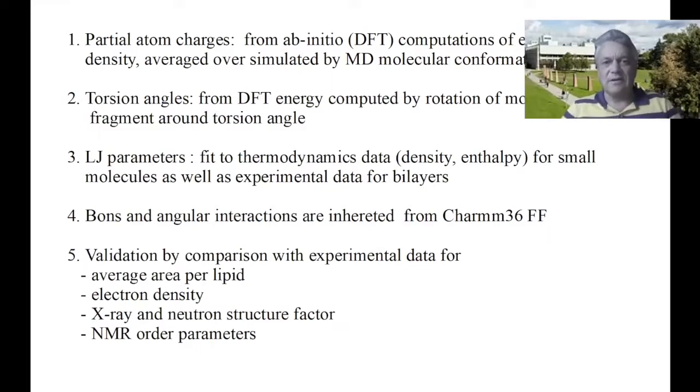Also, torsion angles are very important because the general molecular conformation is determined by the torsion angles. We also computed these from quantum theory: we rotated around the corresponding torsion angle, computed the quantum energy, and fitted torsion parameters to reproduce these quantum energies. But Lennard-Jones parameters were more difficult to fit to quantum theory, mostly because the dispersion interaction of Lennard-Jones interaction is poorly reproduced by quantum chemical theories, density functional theory, or Hartree-Fock theory.